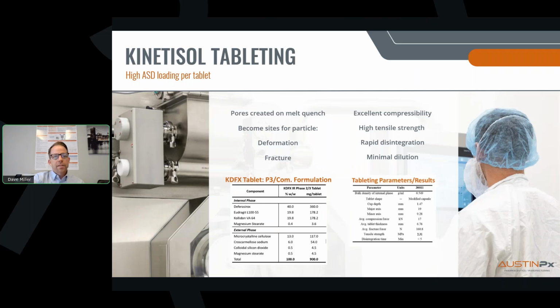This is a case where physics, not just chemistry, is working in our favor. The actual mechanical properties of our particles lend themselves better to tableting. The tables below illustrate this benefit really well. These are from our phase 3 asset, deferasirox. This was a case where KinetiSol was able to generate a 50% drug-loaded ASD using a combination of polymers and ultimately an 80% ASD load in the final tablet to arrive at a 360 milligram unit dose with a 900 milligram compression weight. So that's 40% API per tablet, which is dramatic for an amorphous dispersion dosage form.